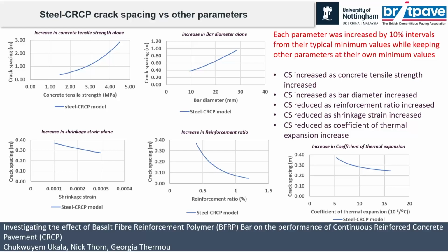And our results showed that for the direct tensile test, or the concrete tensile strength, as it reduced, we expected the crack spacing to reduce. And also, as the bar diameter reduced, the crack spacing also reduced. On the other hand, as the shrinkage strain, reinforcement ratio and coefficient of thermal expansion increased, the crack spacing reduced. So it gave us the sensitivity of what we expect to happen if these parameters were changed.